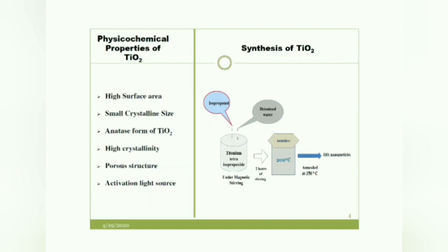The precursor we have used is titanium tetraisopropoxide along with isopropanol and deionized water. They were mixed together in a magnetic stirrer for nearly 2 hours, and then transferred to a Teflon-lined autoclave because we are going for hydrothermal, which is maintained at pressure. Therefore, it is a closed system. It is maintained at 200 degrees centigrade for nearly 4 hours, and then it undergoes centrifuging, and then we subject it to an oven.